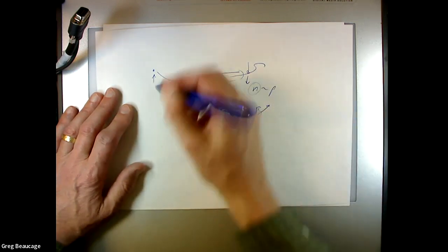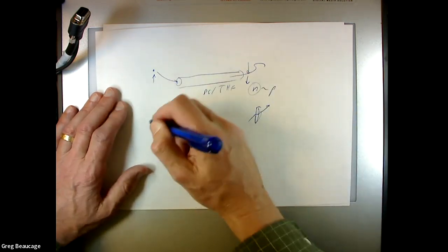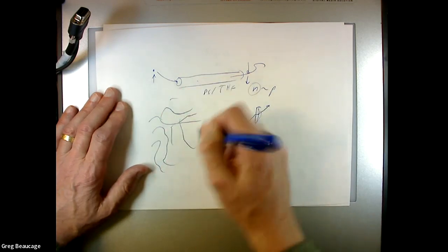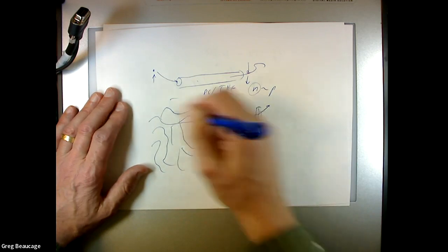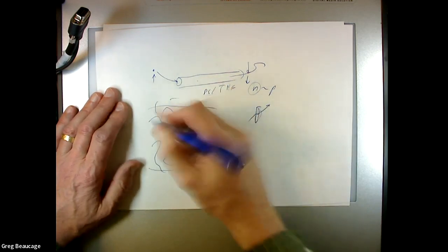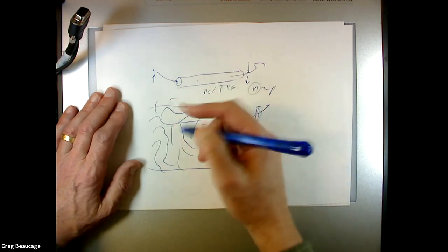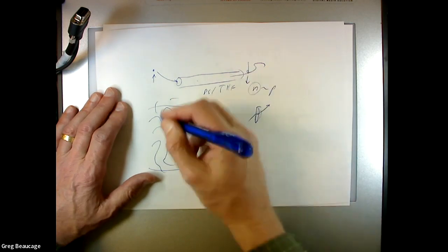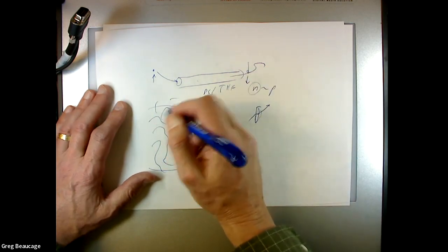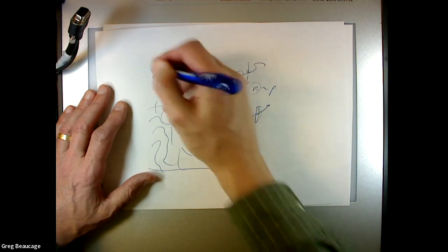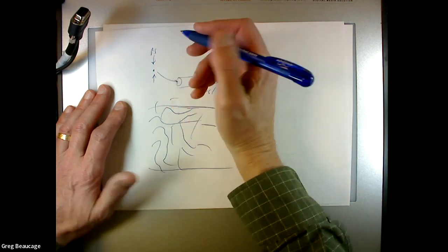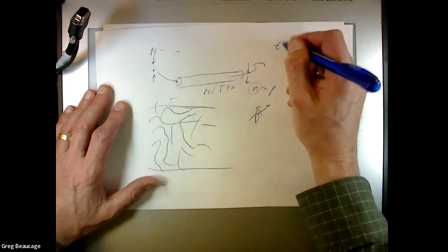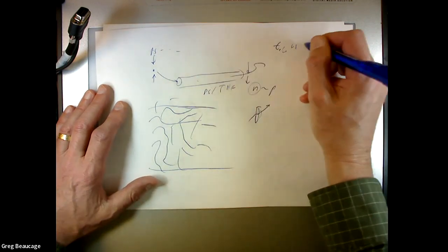how much material is in it, right? It turns out that this gel is like a bunch of passageways, some small, some big. So it's a fractal, some kind of continuous structure to it. It's not really that important, as long as you can calibrate it. To calibrate it, you just stick in monodisperse polystyrene, you put in a bunch of different molecular weights, and you get an elution time versus molecular weight plot.